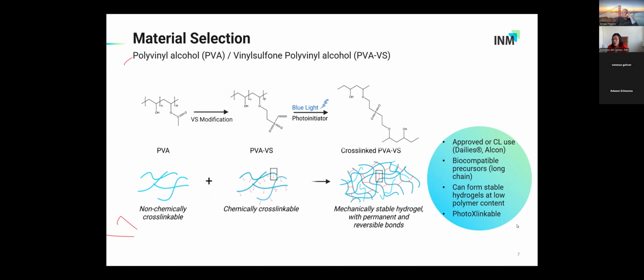We can form stable hydrogels, at least as stable as a contact lens needs to be, with a low polymer content. This is also favorable for keeping the organisms alive. And it's also photocross-linkable, at doses which are compatible with the living system. So it's an approved polymer for contact lenses, which also has good properties in order to combine it with a living organism. And for the next slides, we will be looking at PVA or mixes of PVA with vinyl sulfone PVA, so that we can also cross-link it by photocross-linking. This is the material base we use.